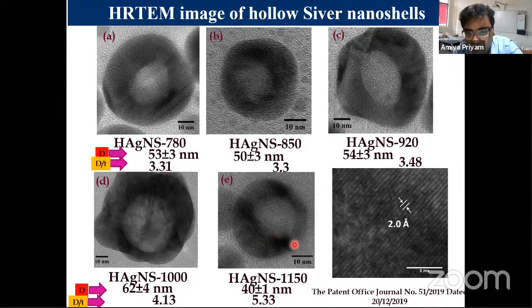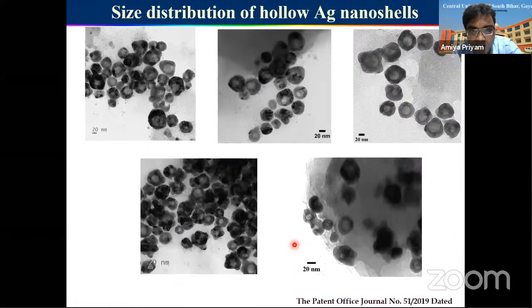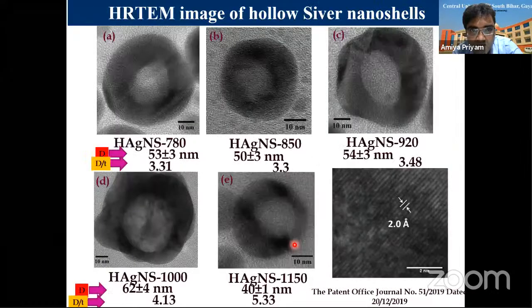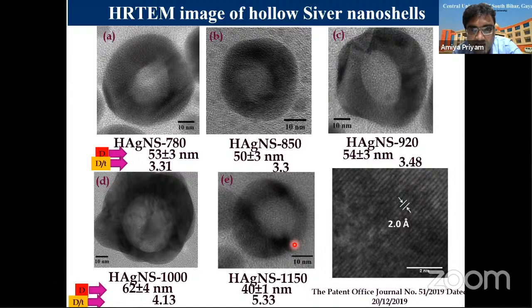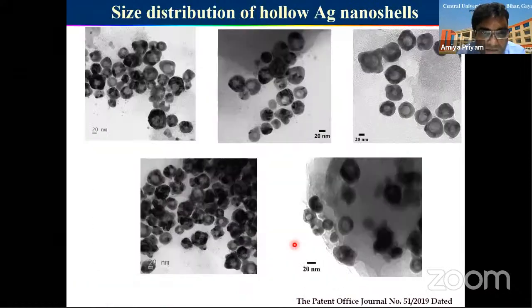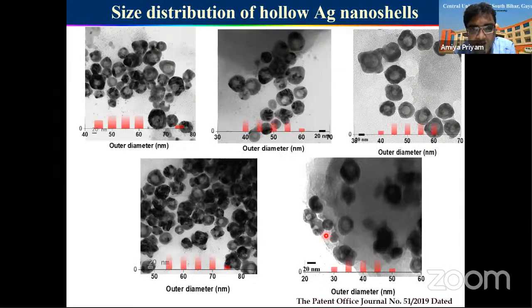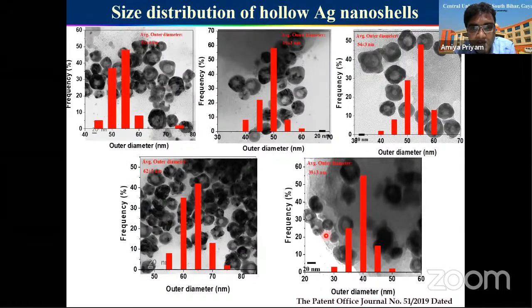We can conclude from these experiments. And so that was the high resolution images of single nanocrystals, hollow nanocrystals, silver nanoshells. And this is the image that shows you the distribution profile. You can see all of them are showing the hollow pictures in all the 5 images. And the size distribution histogram was generated.